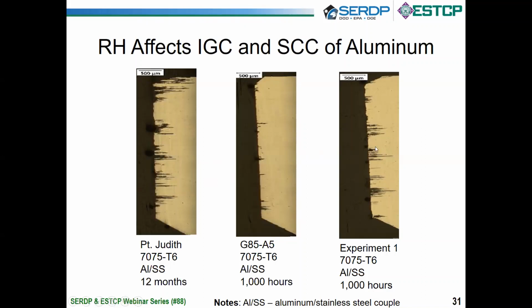Okay, so again, we think this middle relative humidity range, moving into this, accelerates exfoliation, accelerates intergranular corrosion. We think the intergranular corrosion is actually partly related to what's driving the increase of crack growth rates during drying cycles. You see the corrosion happens, and clearly the morphology strongly affects delamination.